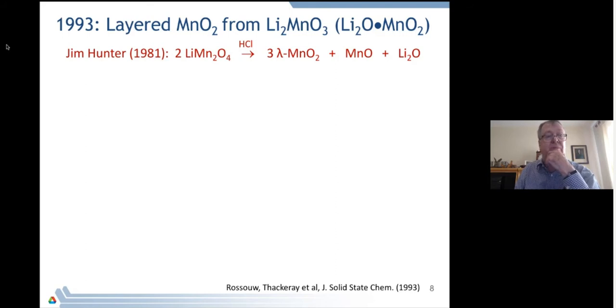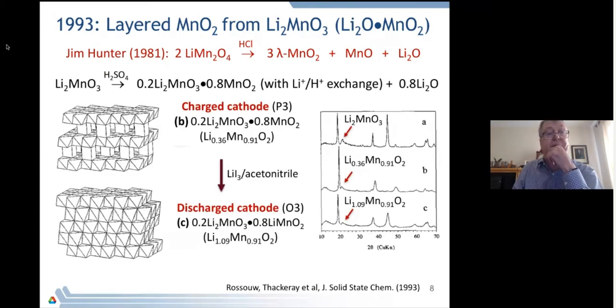It so happened that Jim Hunter in 1981, when we were working on spinels at Oxford, was also looking at LiMn2O4, but in his case, he was leaching lithium out of the manganese oxide to make lambda MnO2 as an electrode for a primary, high voltage lithium cell. But we noticed that this acid treatment leached out lithium during the chemical reaction. And if you look at the formula of Li2MnO3, it's Li2O.MnO2. So we took Li2MnO3 and used sulfuric acid in a similar sort of fashion, to strip out some lithium from the manganese oxide structure. Although this was accompanied by some lithium-proton exchange to yield a charged product that you see on the top left.